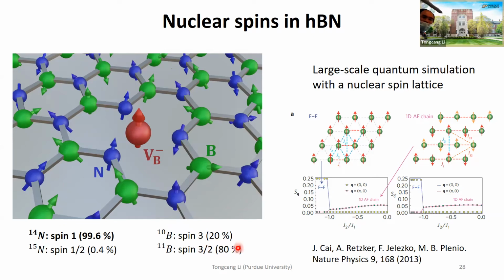For example, here is a theoretical proposal, probably in Nature Physics about 9 years ago. If you have a nuclear spin lattice, then you may be able to do larger-scale quantum simulation. With a nuclear spin lattice, you can also change the orientation of the magnetic field or use a microwave RF to control the interaction between them. Even though the separation is fixed, you can actually change the nuclear spin interaction by tuning the magnetic field or RF. So you can tune them to do quantum simulation and study different phases.